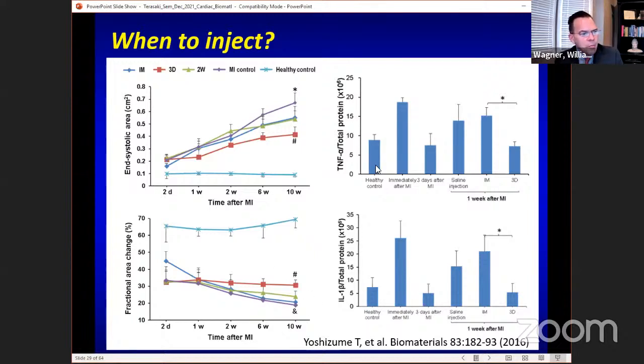And we did some assessment of inflammatory markers. And indeed, at 3 days after MI, TNF alpha, for instance, is lower. IL-1 beta is lower. So it's a different substrate that you're working with when you do those injections. Even if you do it and then look at it later, you've changed that environment.